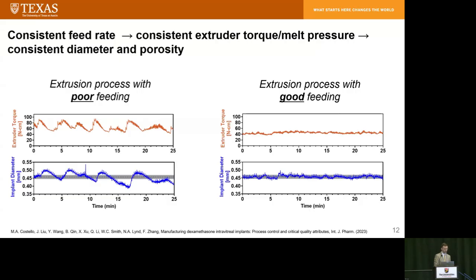So then these charts on the left show the extruder torque and the implant diameter in a process where there's poor feeding, such as in that first extrusion with the fluffy powders. And this chart on the right shows the extruder torque and implant diameter when you run the process with good feeding. So you can see that the torque is very level, the implant diameter is very level, and within that narrow target that we showed earlier.